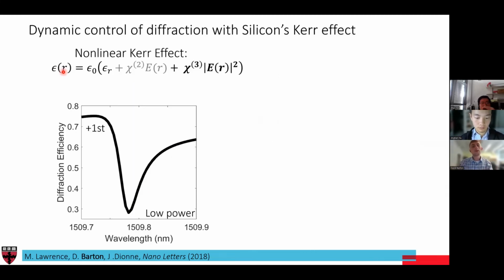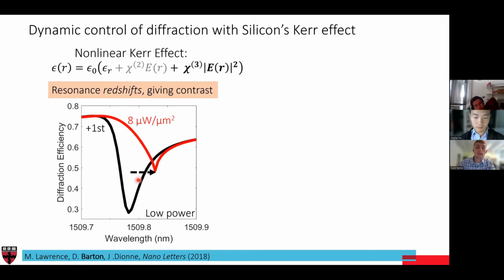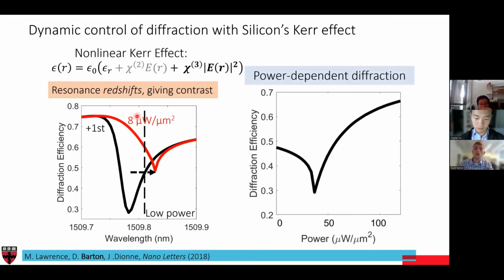And so to demonstrate that, at low power, if we look at the diffraction efficiency, if we increase the power, this resonance will actually shift over because the refractive index is being changed. And in doing so, if we actually look at a particular wavelength and see what happens as a function of power, we can dynamically change what the diffraction actually looks like and what the wavefront shaping is doing, simply by using power as the tuning knob. And so in this case, we can turn on and off the ability to redirect light to a particular wavelength. But we can also do even more than that.